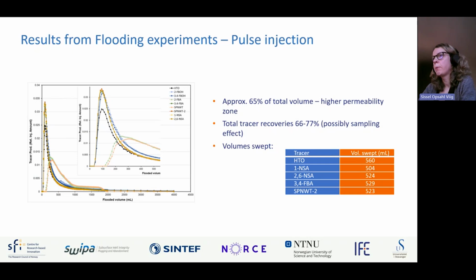And I switch to the next slide where you see results from a pulse injection of the tracers. Here we also see that most of the tracers follow the same trend as the ideal reference tracer, except for the two same tracers that we saw on the previous slide that have a deviation from ideal behavior and are retained through the system. Again, we see that a big part of the tracer signal is a steep pulse, a sharp curve, which is the tracers moving through a high permeable channel. And then we have this long tail indicating that it's low permeability zones where the tracer continues to move through for a long time period, even actually after we stopped collecting samples.